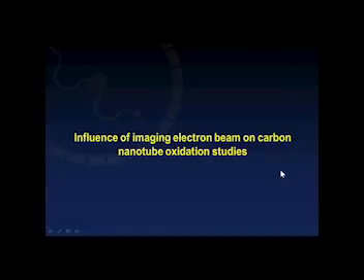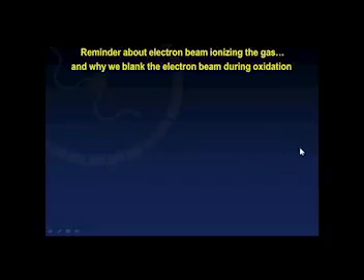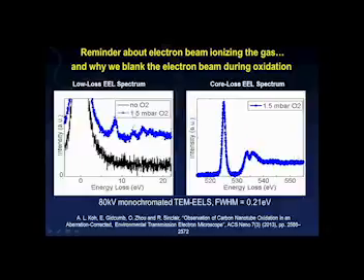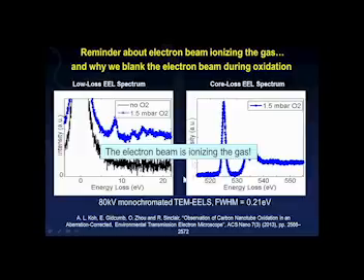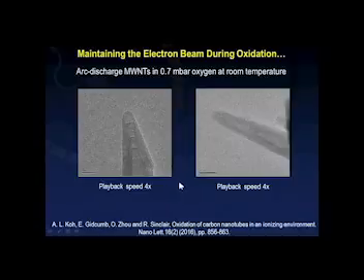However, the situation is very different when we have the imaging electron beam illuminated when oxygen is flowing inside the column. So a reminder again about the electron beam ionizing the gas. When we have gas flowing inside the ETEM column, by means of EELS we can see the ionization edges of oxygen in the spectrum, which indicates that the electron beam is ionizing the gas. If we keep the electron beam on during an oxidation experiment, these are examples of movies of nanotubes imaged in 0.7 millibars oxygen, this time at room temperature, when oxygen and carbon are known not to react at these conditions. We find that if we keep the beam on when oxygen is flowing,